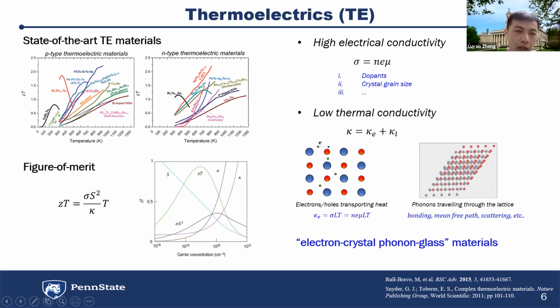And also there are some semiconductor polymers, this is PEDOT:PSS. The reasons why they are working on this material is that they can be flexible, first, and also it's easy to fabricate. They can be solution processed, plus the thermal conductivity of this material is kind of low compared to the traditional TE materials. This is good to generate a high ZT value. But there are also some problems that need to be addressed for semiconductor polymers.